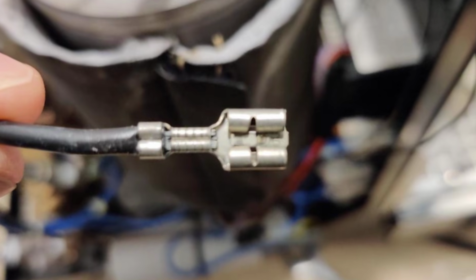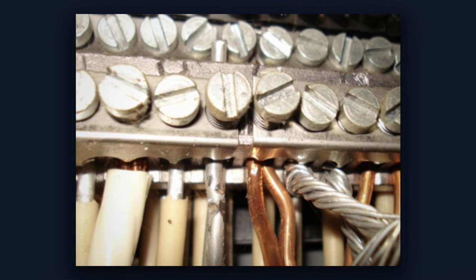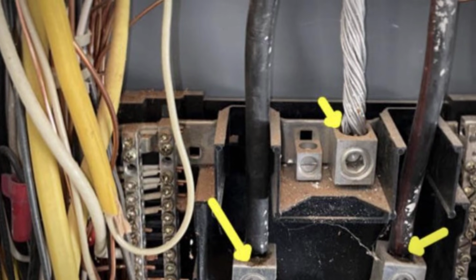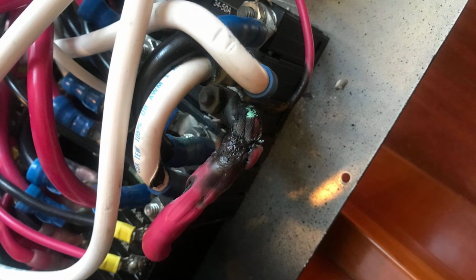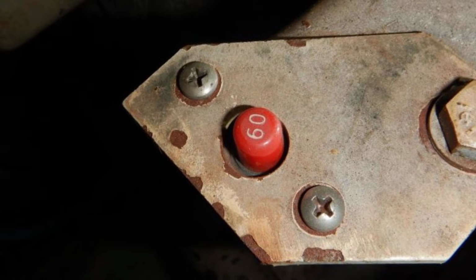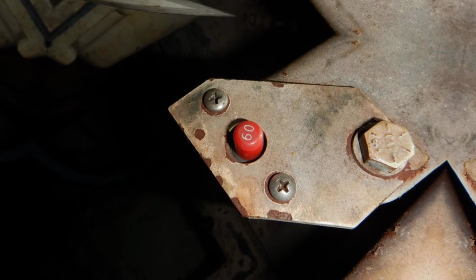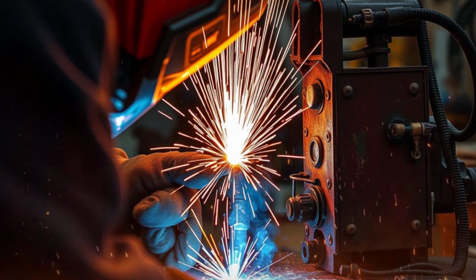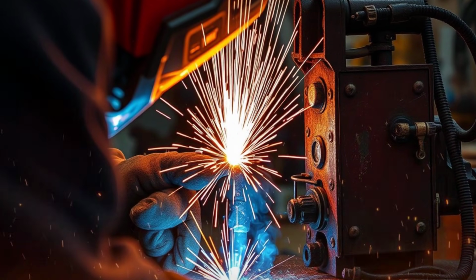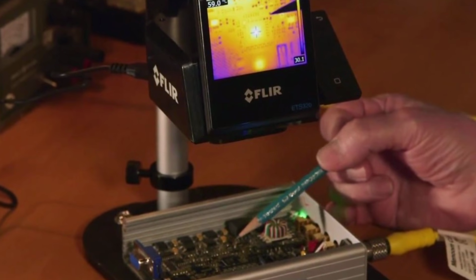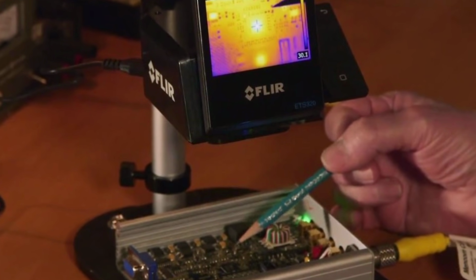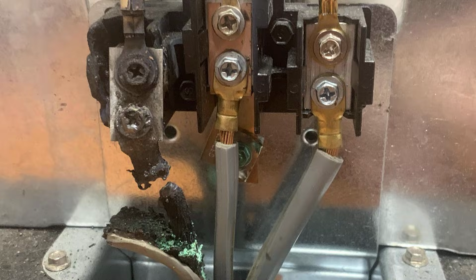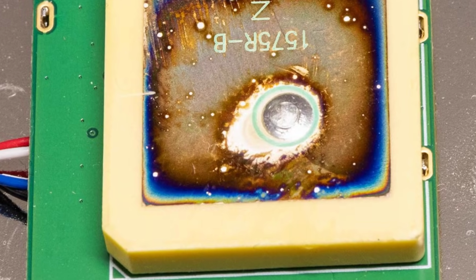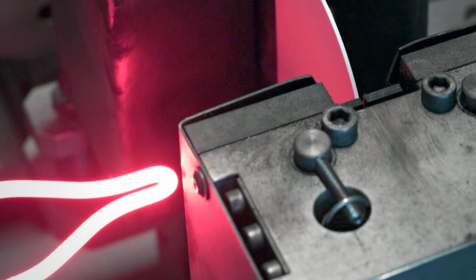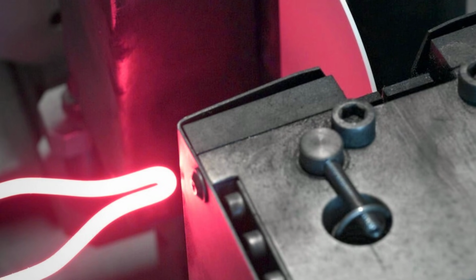A single loose connection is all it takes. As the aluminum wire creeps away from the terminal, resistance builds at the contact point. What begins as a slow, invisible decay suddenly crosses a threshold. The connection, now insulated by oxide and corrosion, becomes a bottleneck. Current tries to force its way through microscopic gaps, and the metal heats up. At first, the temperature climbs quietly, 50, 100, then 200 degrees Celsius. But resistance is not a break, it is a fuse. The heat accelerates, feeding back into the wire, and the cycle turns vicious.